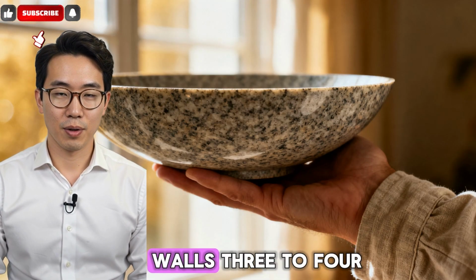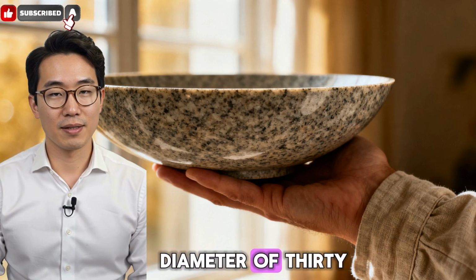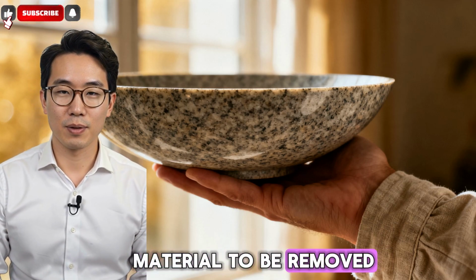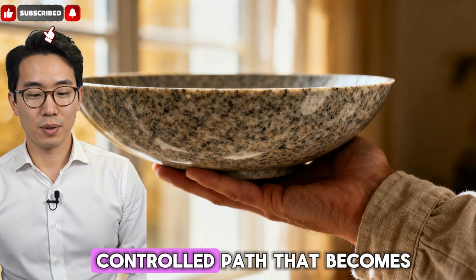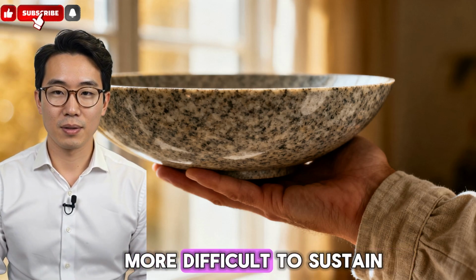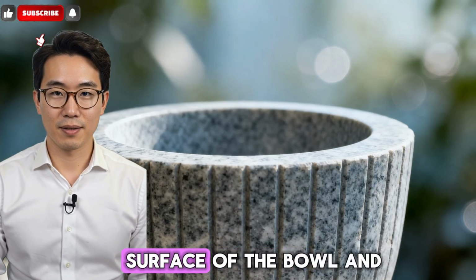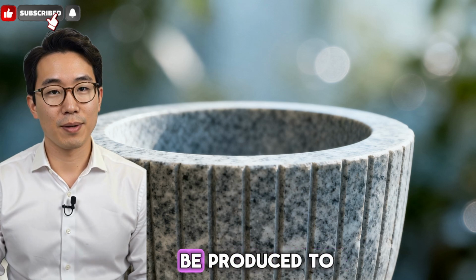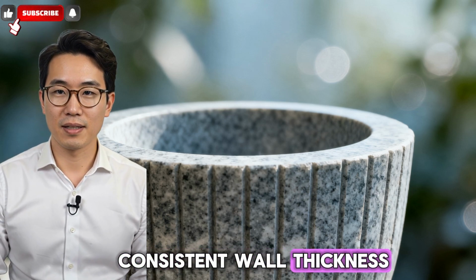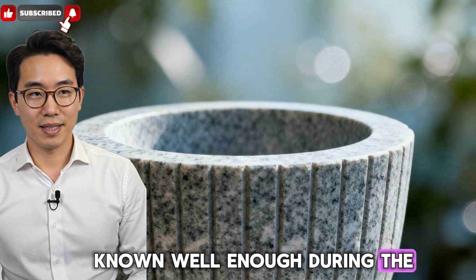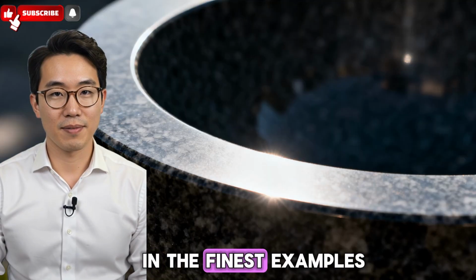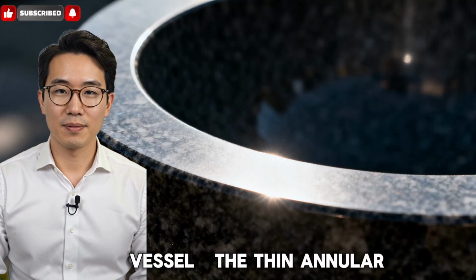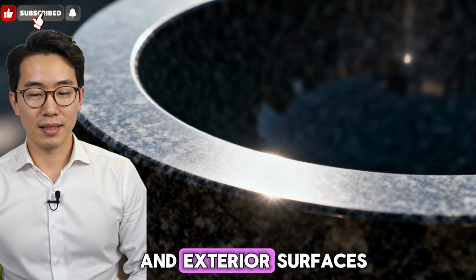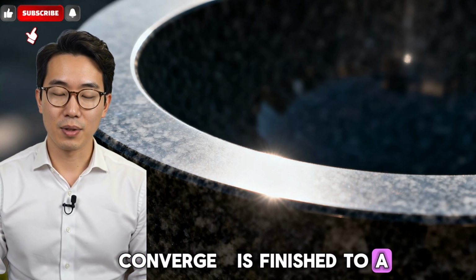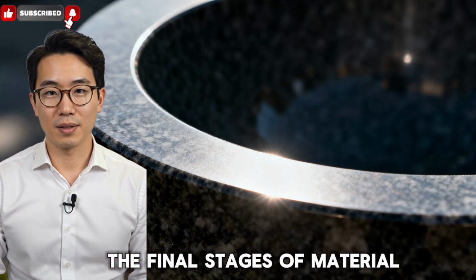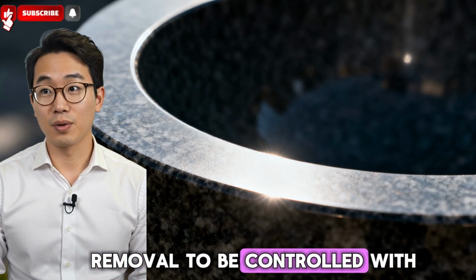A granite bowl with walls 3 to 4 millimeters thick across a diameter of 30 centimeters requires the material to be removed from the interior in a circular controlled path that becomes progressively more difficult to sustain as the walls thin. The outside surface of the bowl and the inside surface of the bowl must be produced to consistent wall thickness. The exterior geometry must be known well enough during the interior drilling to know when to stop. In the finest examples, the rim of the vessel, the thin annular edge where the interior and exterior surfaces converge, is finished to a sharpness and regularity that requires the final stages of material removal to be controlled with exceptional precision.